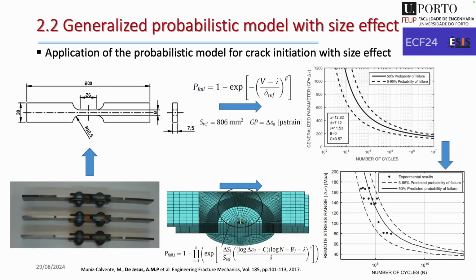Doing that, we started to model the fatigue behavior of some components. At that time, I was working on riveted joints, so we were modeling the fatigue behavior of riveted joints starting with the material properties. We start with simple, smooth specimens, we test those specimens, and we extract the reference probabilistic S-N field. Then, using numerical modeling of the joint and the weakest link theory, we are able to predict the fatigue crack initiation for this joint, as you can see on the right. So starting with material characterization, we jump to the component prediction.